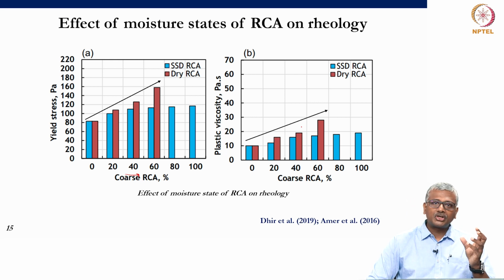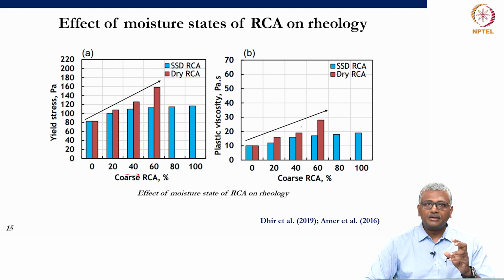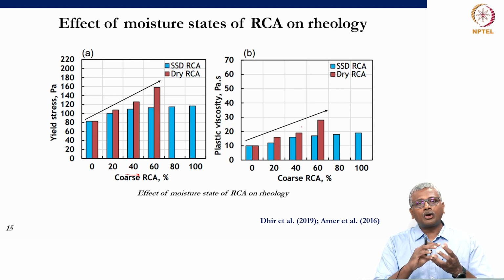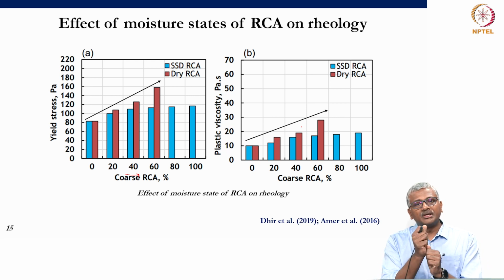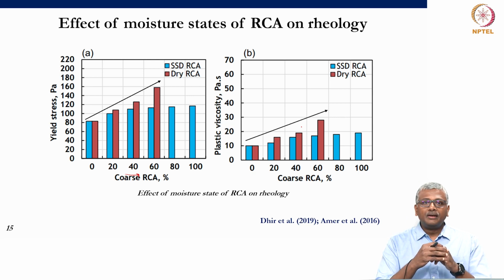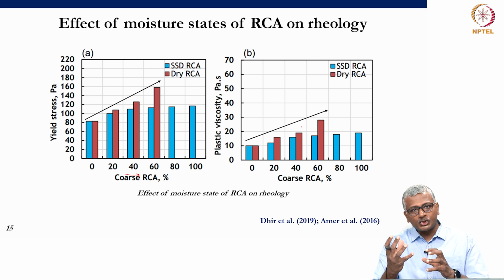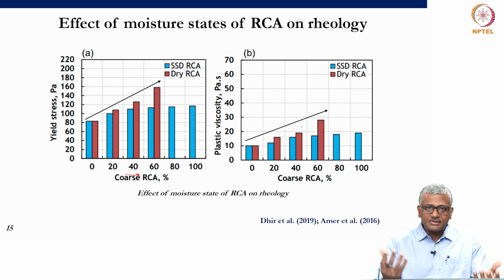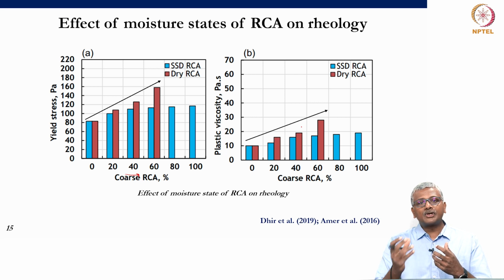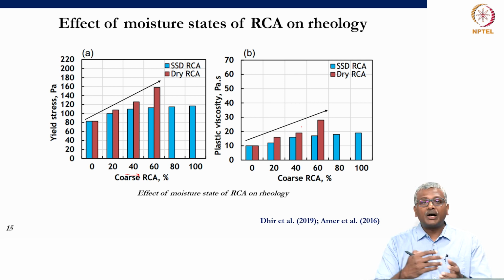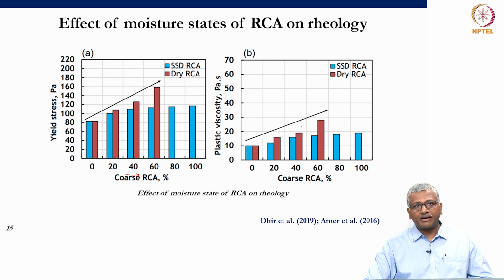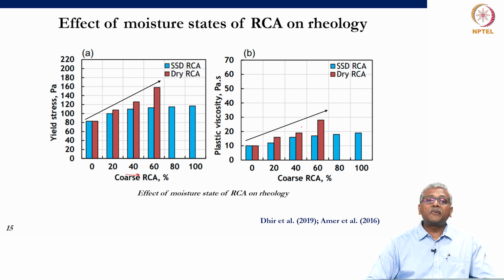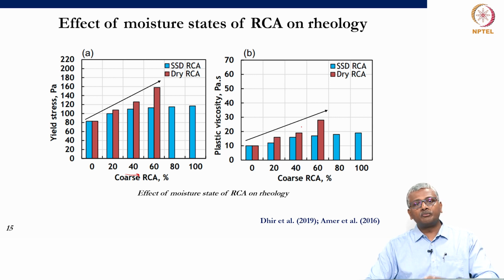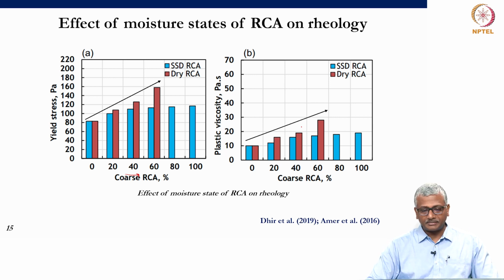When you compare the texture of the recycled concrete aggregate as opposed to a natural aggregate, you can imagine that there will be a lot more roughness on the surface because of the adhered mortar. The shape will not be as well defined, because of which the intergranular friction is going to go up. Okay. Now, this adhered mortar, which is porous, will also tend to absorb some of the water and cement paste from the surrounding paste. Now, as a result, the viscosity of the paste also will go up, and that will lead to a higher plastic viscosity also in the system. Okay. So, when normal aggregate is replaced by recycled concrete aggregate, you can expect a change in the rheological behavior of the system in terms of both an increase in the yield stress and an increase in the viscosity.